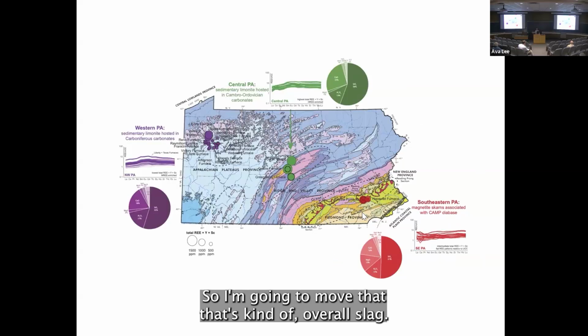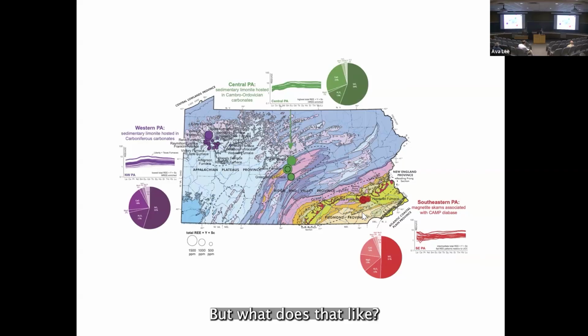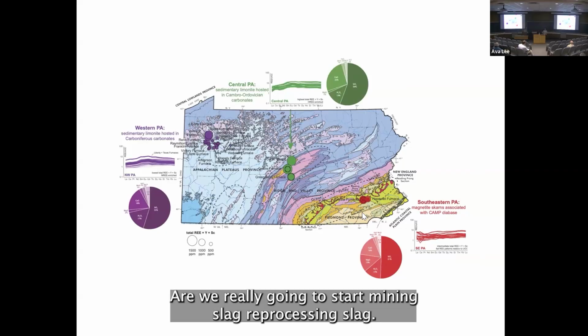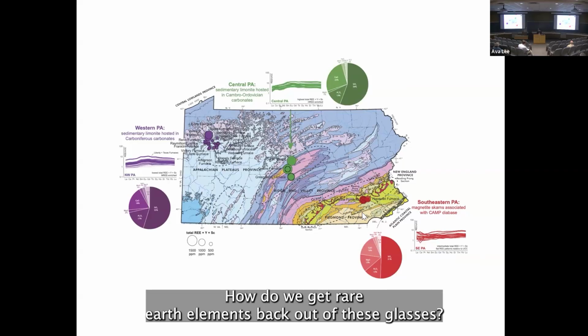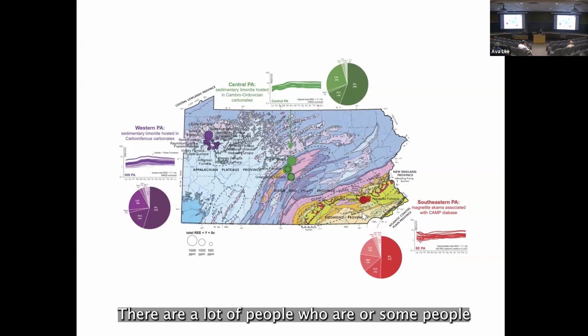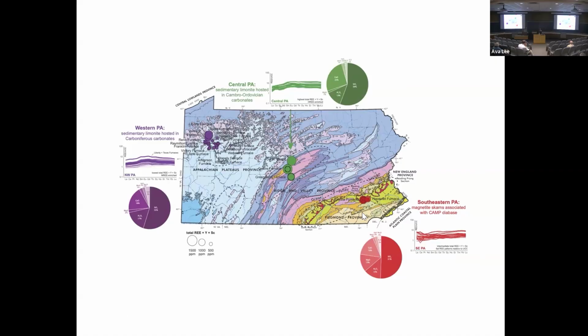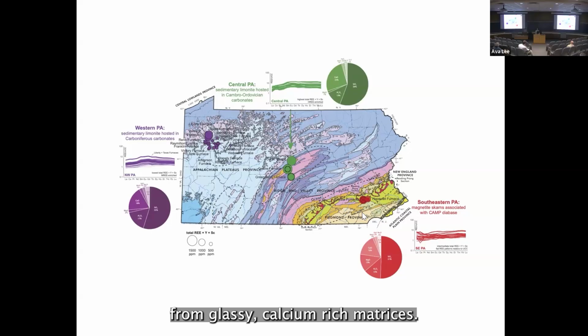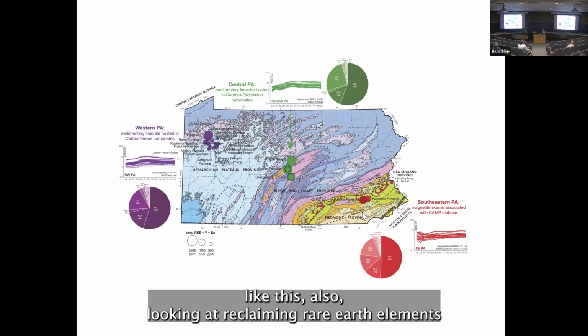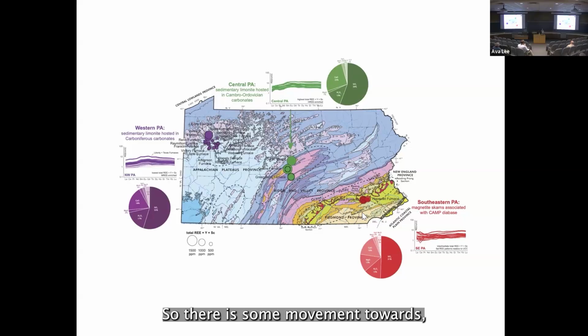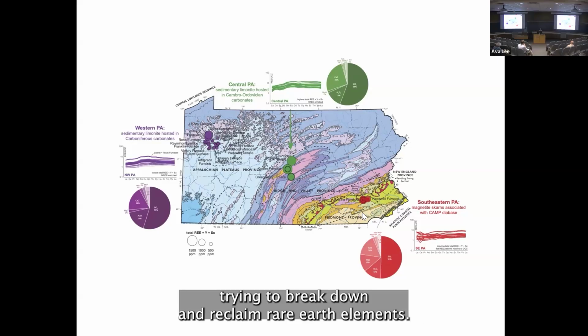All right, so that's kind of overall slag, but what does that mean? Are we really going to start remining slag, reprocessing slag? How do we get rare earth elements back out of these glasses? There are some people who are working now on processes to reclaim rare earth elements from glassy, calcium-rich matrices. In addition to iron slags like this, also looking at reclaiming rare earth elements from fly ash, which is compositionally similar on the whole. So there is some movement towards trying to break down and reclaim rare earth elements.